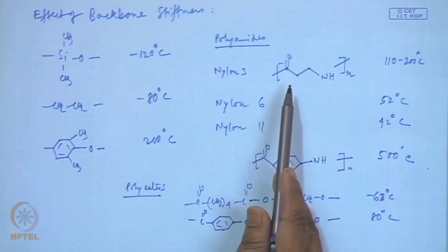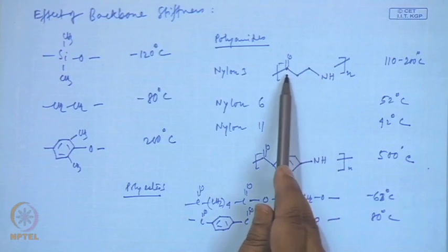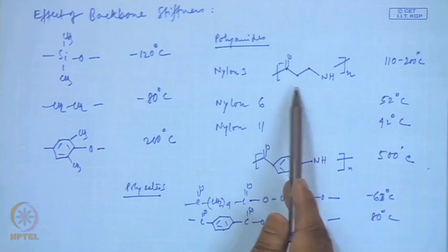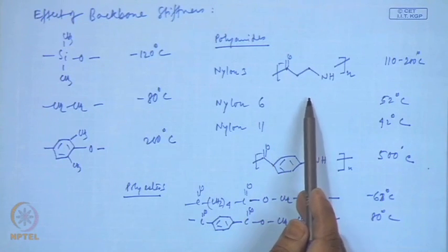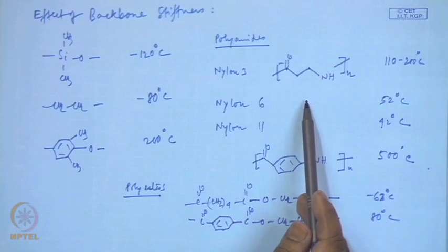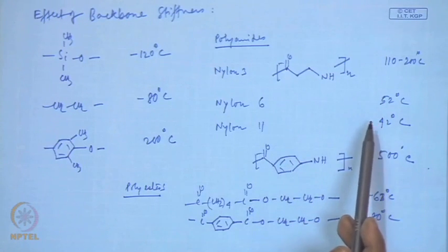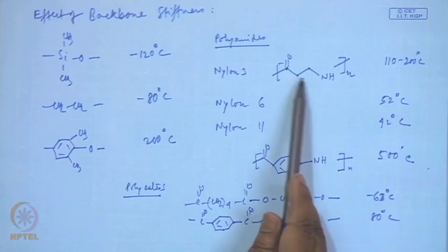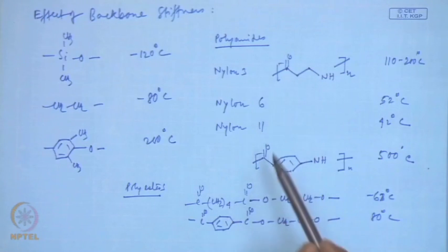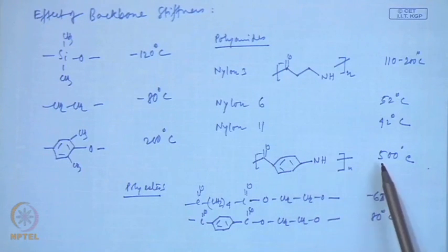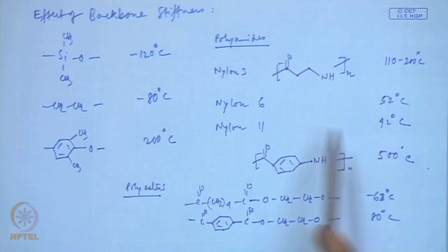Similarly, here, these two are stiff components. So, the more CH2 groups we put in between, the more flexible or less stiff the polymer chains are. So, Tg comes down, whereas if instead of a non-polar alkyl chain in between you have rigid aromatic groups which restrict the rotation around the single bond, the Tg drastically goes up.